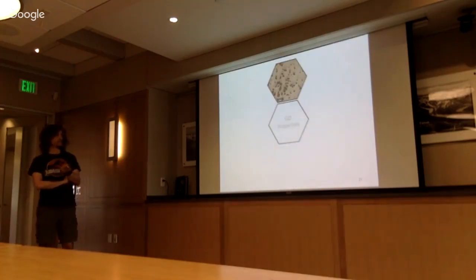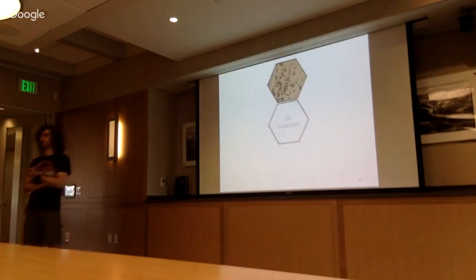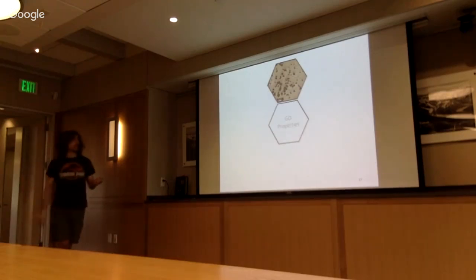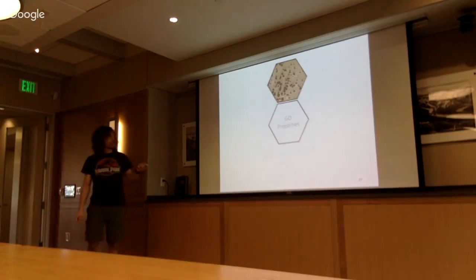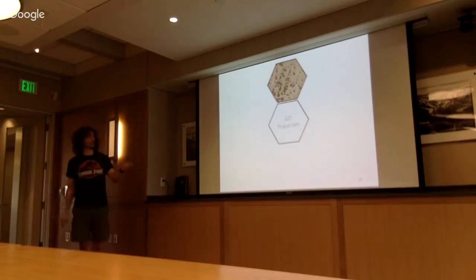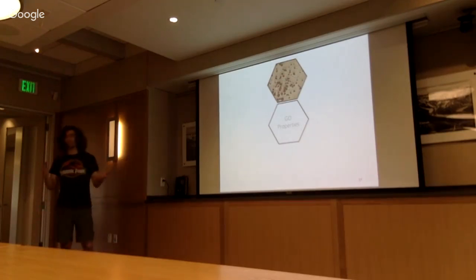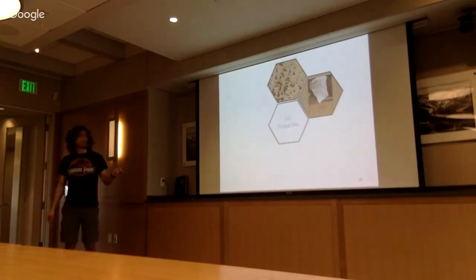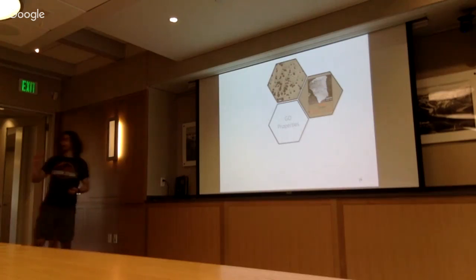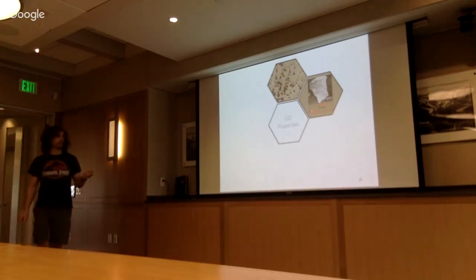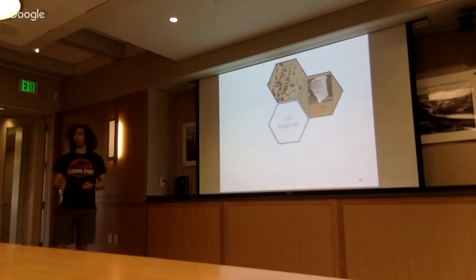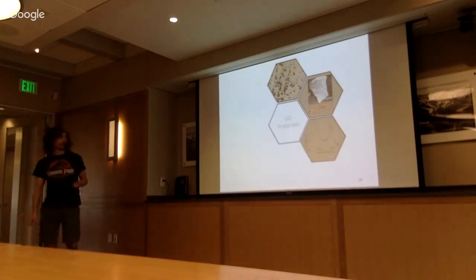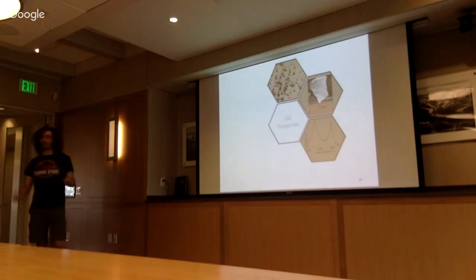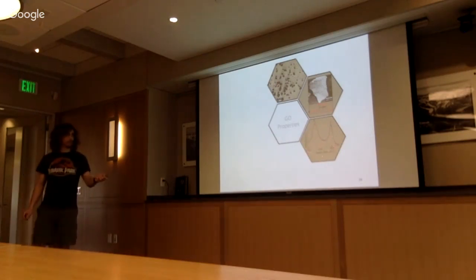And this is just a figure to represent all the properties of graphene oxide. With scanning electron microscopy, we can get some images of the single flakes, and we can see the scale bar is basically a tenth of a human hair. We can see that the flakes are micrometer size. With atomic force microscopy, we can check the thickness of this material, and we can see that it's actually a monolayer, and the thickness is between 1 to 2 nanometers. With Raman spectroscopy, we can check the sp2 nature of the material through the G peak.